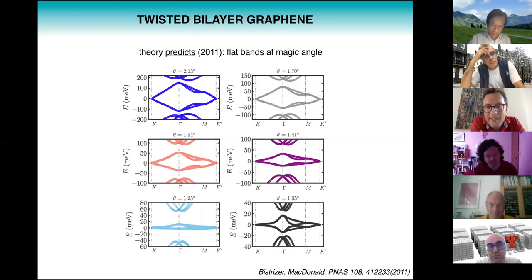You're absolutely right. But if you calculate the band velocity, it is still true that at the magic angle, the band velocity goes to 0, right? So if you turned off interlayer coupling and you calculated the band velocity as a function of twist angle, it would always be the same as that of graphene. But if you actually turn on interlayer hopping, you can see that the band velocity actually goes to 0 at the magic angle. So I'm talking about the slope of the band.